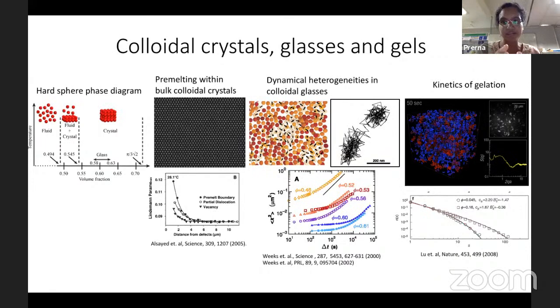Whereas at the same volume fraction of 64%, if you put the particles in a crystalline geometry, you will have enough space to rattle around. So that's the argument. Here there is no orientational entropy. There is a configurational entropy and there is a vibrational entropy. In the rod-like system, we had orientational and translational entropy. Configurational entropy means in how many different ways you can arrange the particles. So of course, fluid will have very high configurational entropy compared to a lattice, because a lattice is one regular arrangement. But at these high volume fractions, fluid is going to have lower vibrational entropy, and that's why the crystalline phase becomes stabilized in this hard sphere geometry.